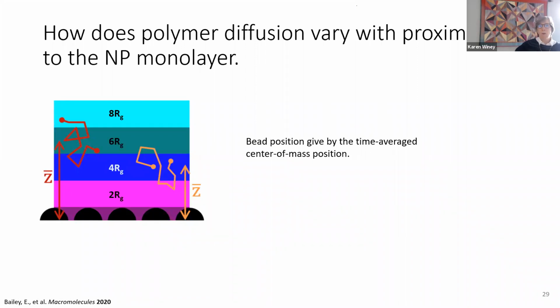Okay, but the focus of doing all of this was the diffusion. So now that we have this monolayer, we can look at the diffusion at different distances from this monolayer. And so we look at the dynamics of individual beads in the melt, and we look at a whole trajectory of one bead, and we see what is its average height, its average Z distance above the monolayer. And we assign it that Z value, or its average Z value over the course of its trajectory. And then we can think of these different bands, right? 2 RG away, well, inside the layer is the dark purple, and then different distances away from the monolayer. Okay. So we can look at diffusion coefficient as a function of distance from the monolayer.